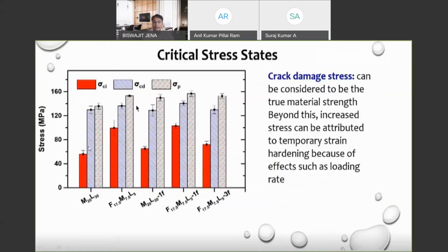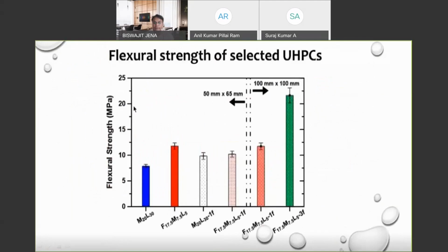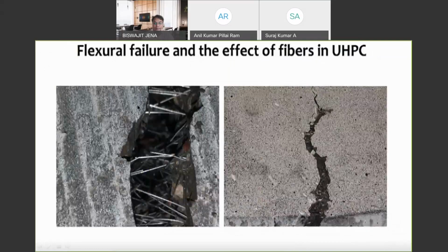Next we will go for flexural strength of ultra high performance concrete. Generally 20 to 25 megapascal of flexural strength for these materials, and if you have fiber reinforcement, extremely high flexural strength. So here you can see the effect of fibers again. You see here the fibers bridging the cracks. A lot of fibers in flexural failure.